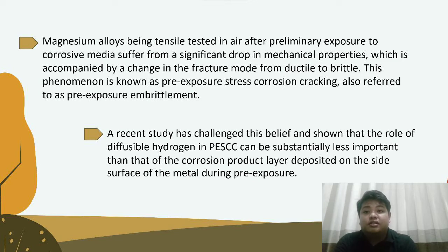A recent study has challenged this belief and shown that the role of diffusible hydrogen in PESCC can be substantially less important than that of the corrosion product layer deposited on the side surface of the metal during pre-exposure. In particular, it was reported that PESCC in the alloys ZK60 and AZ31 preliminarily immersed in the NaCl-based corrosion solution was completely eliminated by the chemical removal of the corrosion product layer, provided that irreversible corrosion damage was not too high.